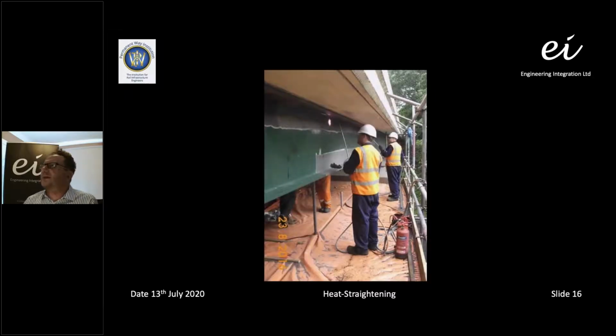So this is the operation being undertaken. As you can see, there's very little removal of paint that we've had to undertake to allow the heating process to be undertaken. The heating areas, we remove by blasting all of the paint within the proposed heating areas, and then we apply the heat using oxyacetylene torches. You can see there that we've used scaffolding in this instance for the operatives to gain access to the structure. This isn't ordinarily the case. It's just that the Highways Agency in this instance was able to give us full road closure. Therefore, it was most practical to provide scaffolding in this scenario.